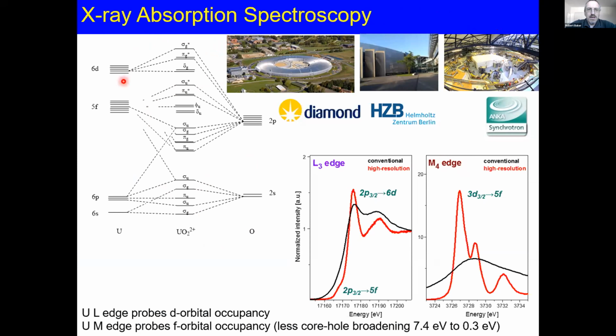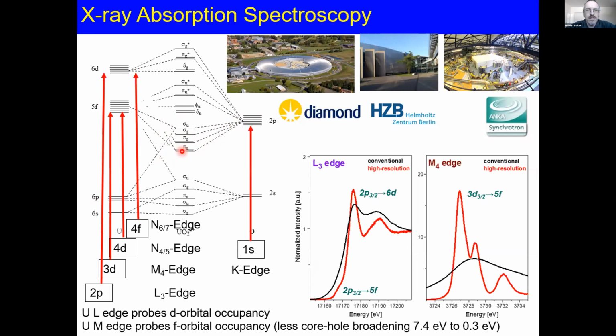So to understand the spectroscopy, this is the MO diagram for a uranyl ion. We have some semi-core involvement of the 6p orbitals, which means that unusually the sigma orbitals are higher in energy than the pi orbitals. But this is where this covalency comes into effect, forming the uranium-oxygen bonds. And we can use a number of different edges in theory to look at both the d and the f orbital contributions to bonding, as well as the ligand-based K-edge spectroscopy. So the commonly used L-edge probes d orbital occupancy, M-edge probes f orbital occupancy.